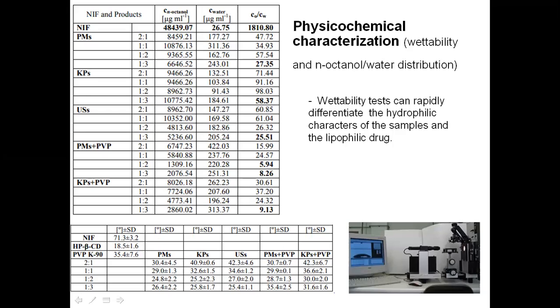The wetting angles of the investigated products in all cases lay between the values for cyclodextrin and niflumic acid, and the investigation of the systems produced by the different preparation methods revealed that with increasing hydroxypropyl beta cyclodextrin content, the contact angles decreased, and usually the 1:2 and 1:3 ratios gave better results.